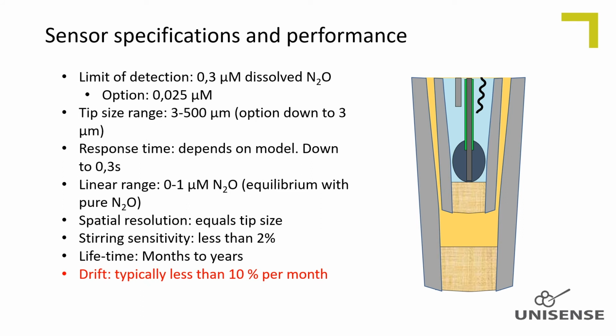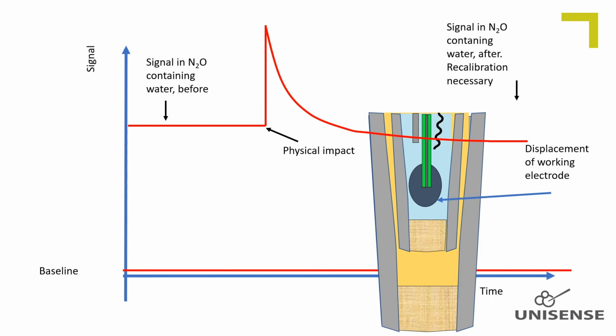Typically, the signal does not drift more than 20% in the lifespan of the sensor, so the weekly to monthly drift is minimal. The baseline does not change significantly with time. Physical impact to the sensor can, besides destroying the sensor, change the sensitivity and thereby the calibration curve of a nitrous oxide microsensor. The working electrode connects to the amperemeter via a thin, flexible glass-covered platinum wire. Physical impact, which shocks the internal components, can induce a displacement of the working electrode position relative to the membrane, thereby changing the sensitivity. Typically, such impact will induce a sudden signal peak followed by a stabilization time, but the sensitivity might not return to the original sensitivity caused by a displacement of the working electrode position. The baseline is typically not affected.